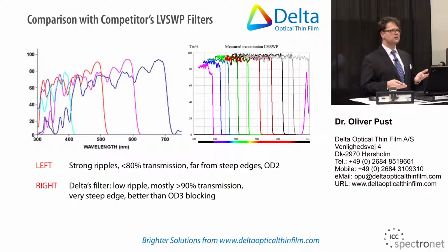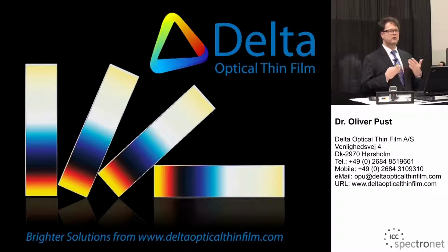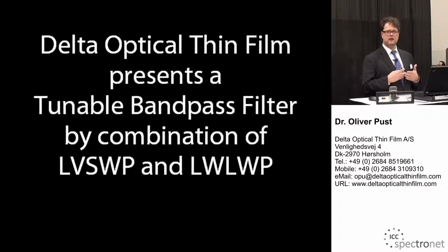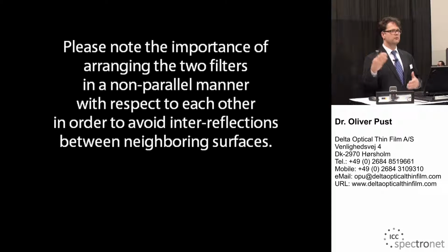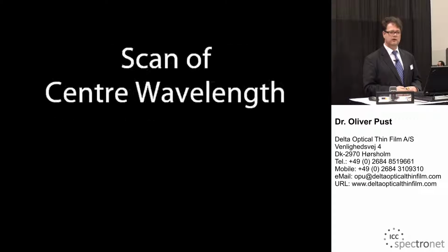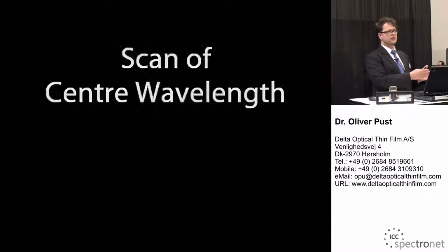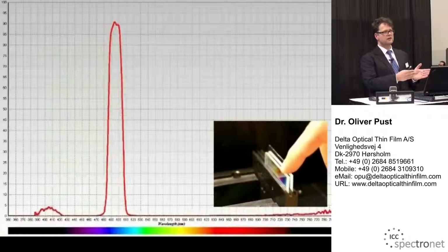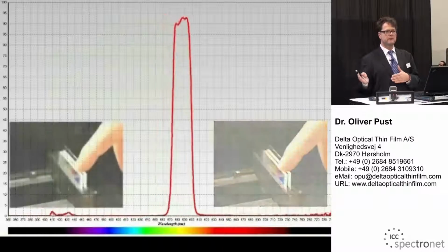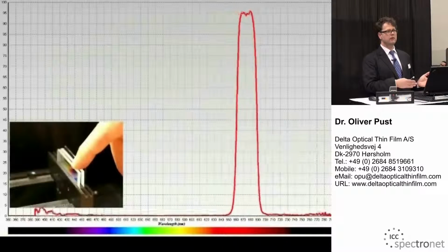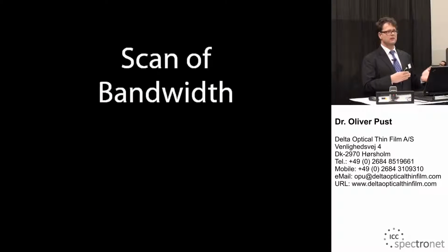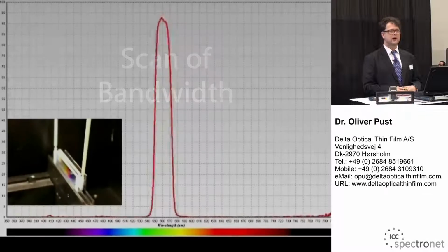In this animation, I show you how you can combine these two filters to make a fully tunable bandpass filter by moving them with respect to your light source. And in good optical practice, you want to angle them a little bit to avoid interreflections. In the first sequence, we move the filters synchronously through the beam path, and that changes the center wavelength continuously between 300 and 850 nanometer.